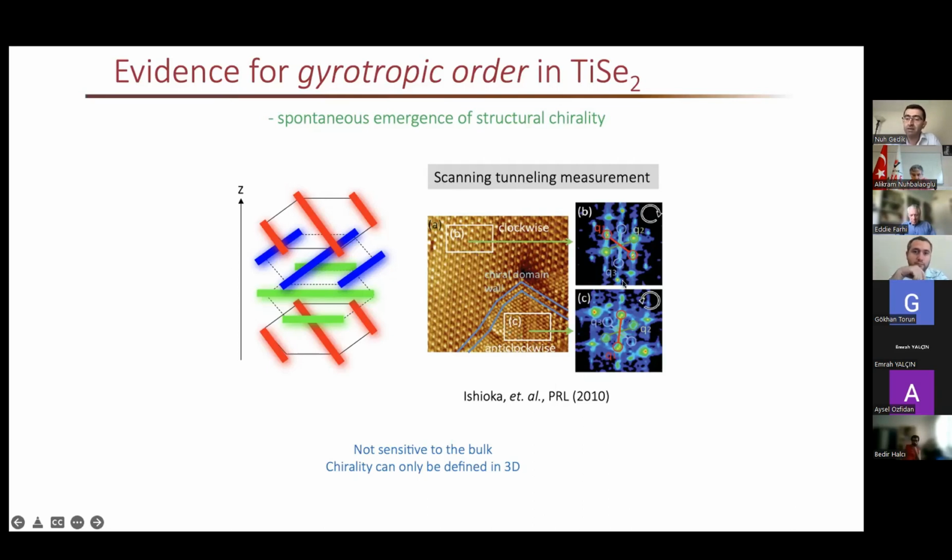In both of them, they do see these 3 different charge density waves, Q1, Q2, and Q3. The brighter spots are the atomic Bragg peaks, and the spots inside come from these 3 different charge density waves, 120 degrees to each other. So the 2 domains are the following. In domain number 1, you can see that there's Q1, Q2, and Q3. This is the most intense one, this is the medium one, and this is the weakest one. So there's this chirality to this. It goes from intense, to less intense, to least intense.